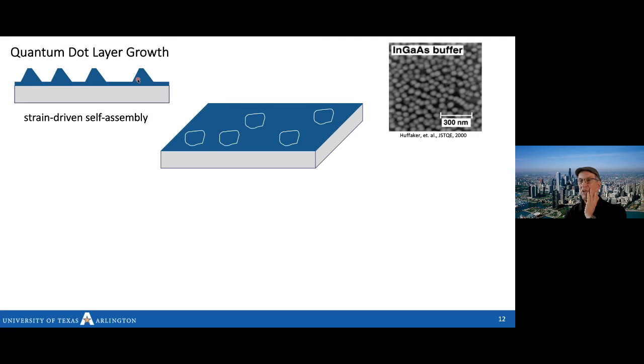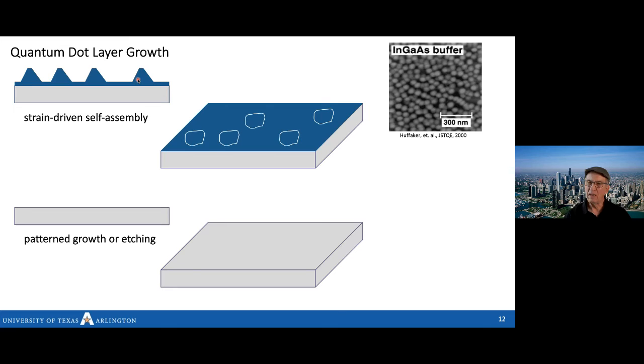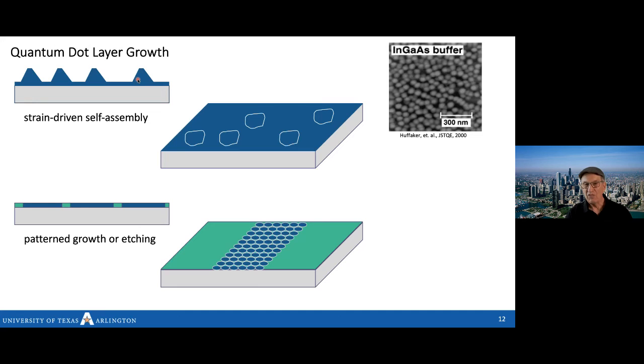There's some variation in the size, but it's easy enough to see that these things are in the 30, 40, 50 nanometer diameter. And they're sort of randomly distributed. We had interest in avoiding the random variations in size, so we started making quantum dots by pattern growth or etching, and this is using silicon processing technology. Put down an oxide on a semiconductor and pattern some holes in it, and then grow the material in there. What we found is there's some irregularity just because there's limits to how precisely you can do the patterning. But when you etch away the oxide, it leaves behind some variation in size, but absolutely no variation in distribution because the patterning is so clear.